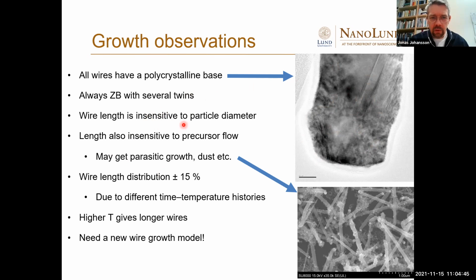Wire length is insensitive to particle diameter and precursor flows, but we can still get parasitic growth if we have too high pressures. And there is some wire length distribution. And we have experimented a little bit, and we find that this broadening is not due to any Poissonian broadening, but to different time temperature histories in the reactor. And as we saw, higher temperature gives you longer wires. So this growth rate being insensitive to pressures and particle diameter called for a new wire growth model.